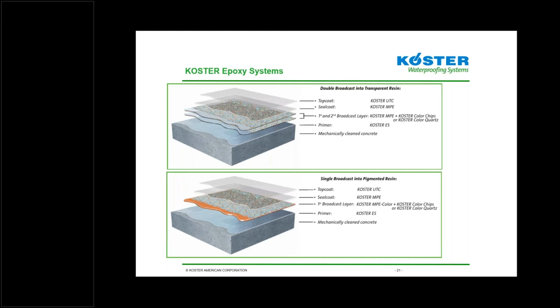Normally, the difference between a double broadcast and a single broadcast is not only in terms of physical performance and impact resistance, but with a single broadcast system, like we see on the bottom of the slide here, we would normally use a colored body coat to broadcast into to help prevent any of the floor or the concrete substrate below from coming through the finished floor. When you do broadcast flake and quartz into these systems with only one broadcast, there may be holidays or voids where we can see the floor through those areas. That's why in the single broadcast, we would normally use a pigmented base coat to broadcast into. With the double broadcast systems, we can use clear coats to broadcast into, because the double layers of broadcast will hide any holidays or voids that we have.